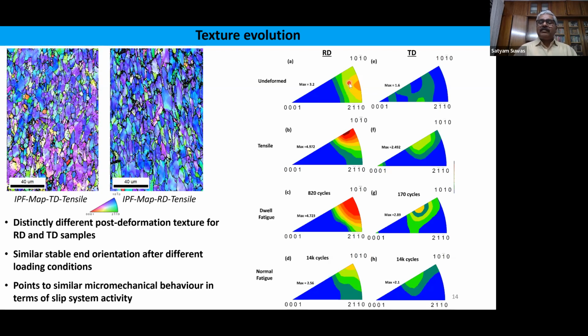And then we could see here the changes in the texture. Like tensile, the rolling direction samples accumulate strain over here. They get oriented mostly after the tensile test along the 10-10 direction, which is expected. And in dwell fatigue, they also accumulate strain along this direction, but under normal fatigue, the texture seems to have weakened. And the TD direction sample never acquires any strong texture.